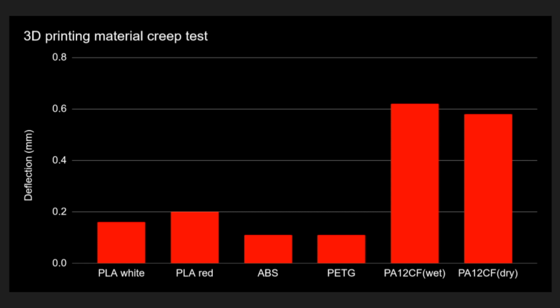And the other surprising result is that the wet one and the dry one don't seem to have much difference in the end when loaded in the room temperature environment. The dry one seems to absorb moisture when loading and performs a similar result to the wet one.